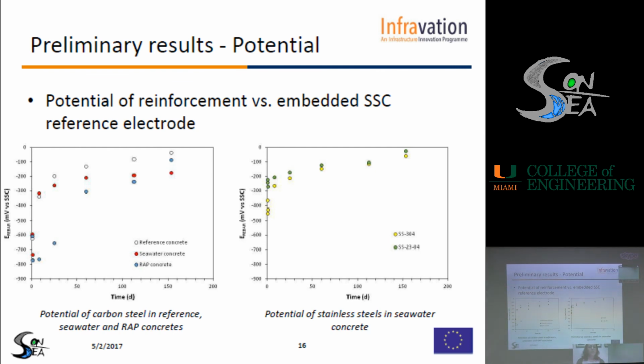the potentials of carbon steel in reference and RAP concrete and also stainless steel are higher compared to minus 100 millivolts. Only the potential of carbon steel in seawater concrete is about minus 200, which is quite lower compared to the others, but still is a relatively high value of potential.